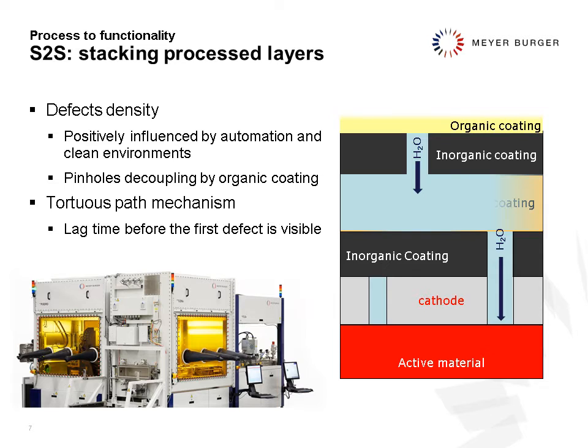So we have this penetration, but what you can also realize is that there is a lag time before the water can actually get there and start a defect. So you not only get a low WVTR, but you get some sort of dynamic one. So it will be zero until this whole story will go through. And even when wet is done, the defect will grow very slowly because of the principle we set.